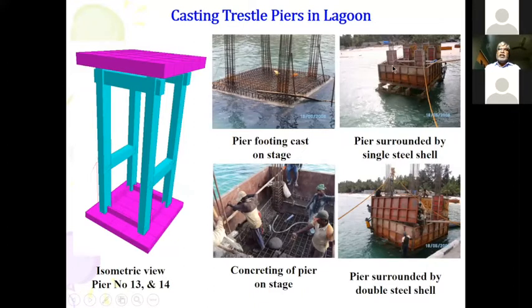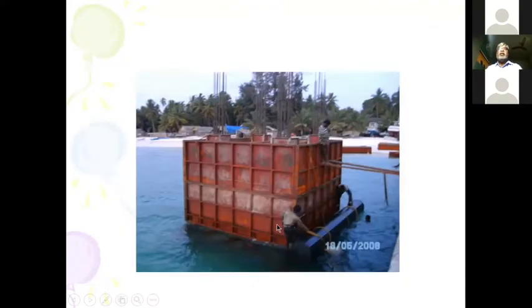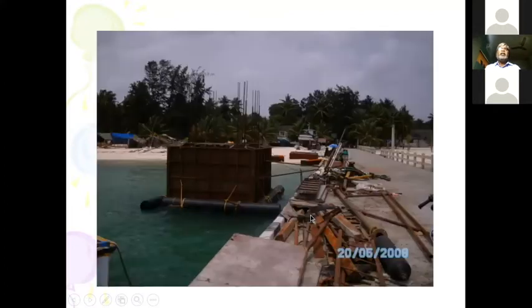So we made the same shuttering formwork system like this all around, and provided the sealant in the joint so that no water gets percolated. And in addition to that, we also used pipes for getting the additional buoyancy force. And once it is done and made perfect, then the partial concreting was done. You can find this for additional buoyancy. We also tie these tubes so that it can flow without any issue.